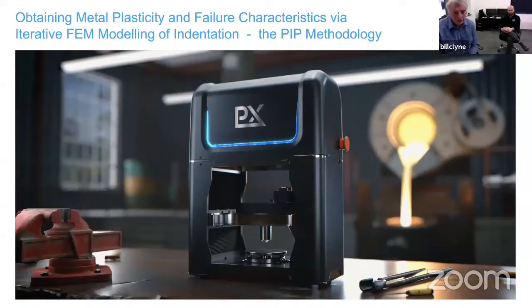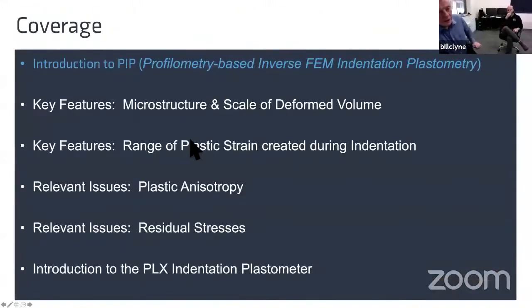So let me just give you an introduction first to what is actually in the talk. So this is the structure. I'm going to start off by just giving some background really to the concept involved. We call it PIP. It's based on making indents, measuring the indent profile, and then doing a repetitive, iterative FEM simulation of the process in order to converge on the best fit set of plasticity parameters. What we're trying to establish is the stress strain curve of the material.